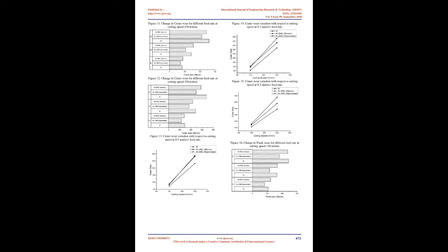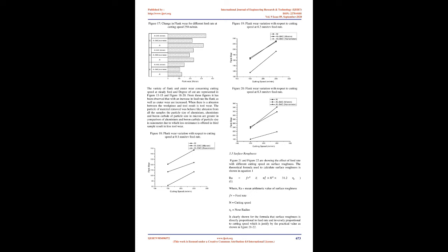Ashutosh Kumar Singh, Deepak Singhal, Ramanujay Kumar, 2019, [7]: This work deals with the machining of aluminum 7075 with copper, brass, electrode using electrical discharge machining process. The impact of EDM process parameters on the different output of workpiece were statistically analyzed with a series of runs. L27 set of experiments are performed with 4 inputs: pulse on time, voltage gap, peak current and flushing pressure, and their 3 levels. By setting the necessary parameters, material removal rate, MRR, is assessed.